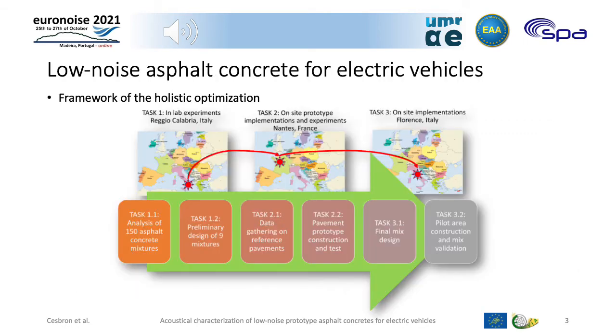The development of the low-noise asphalt concrete for electric vehicles was divided into three main steps. It followed a holistic optimization which was developed by University of Reggio Calabria. In the first step, up to 150 asphalt concrete mixtures were analyzed by the University of Reggio Calabria, and 9 mixtures were preliminarily designed and tested in laboratory. Based on these preliminary results, 2 asphalt concrete mixes were selected for prototype construction in France, in Nantes, on a reference test track at Université Gustave Eiffel.